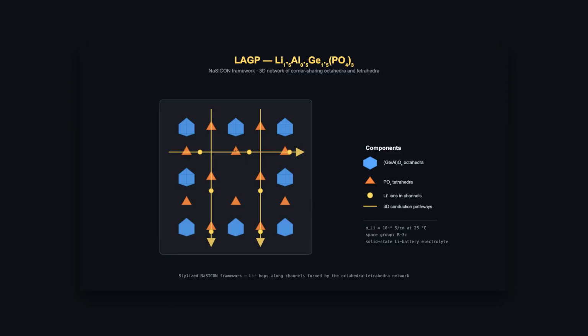Conventionally, you crystallize this glass by holding it at 620 degrees Celsius for 12 hours. Campos and Rodrigues did it in seconds, at 500 Celsius, with 1 voltage pulse. Same gate. The glass has free lithium ions. Its conductivity climbs with temperature exponentially. Arrhenius opens the door. They named the technique Flash Sinter Crystallization, FSC, the first time anyone had crystallized a glass through the flash event itself.